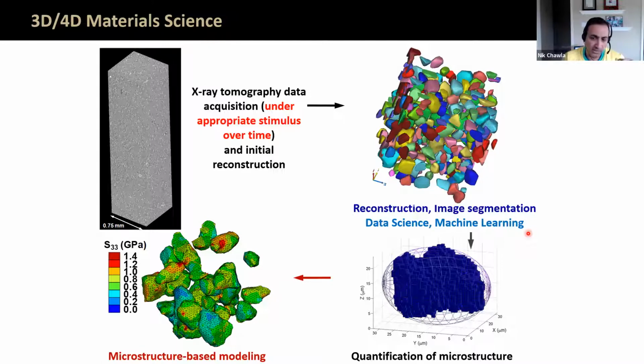And finally, one thing that you can also do is you can take this microstructure and incorporate it into some suitable model. Most people have done some kind of a mesoscale model where you can incorporate the microstructure into a finite element model, and then you can apply appropriate boundary conditions. You can apply crystal plasticity if you have grain orientation information, so on and so forth.